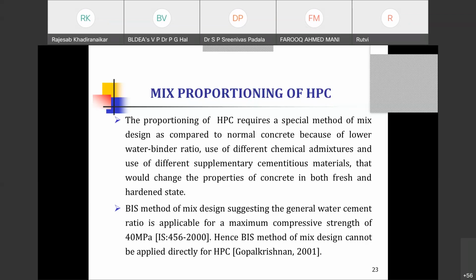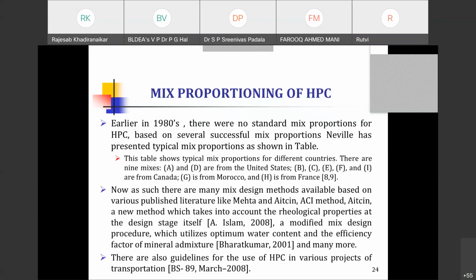So we have a large number of methods already available. Of course, when it comes to the Indian context, we have the BIS method of mix design. And the BIS method, IS 10262, we generally use, but it cannot be directly used for high strength and high performance. Here, the water cement ratio is applicable for up to 40 MPa strength, so it is higher than 0.3 or 0.35. That is why it cannot be directly applied for high performance concrete.